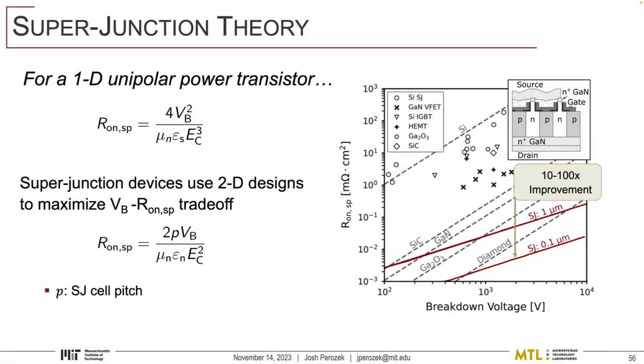But when we do that, we're able to remove this dependency on the breakdown voltage where it's a squared voltage, and we just have a linear dependence with it. That means that as we scale the voltage, the resistance grows much slower. It ends up for gallium nitride at about 1,000 to 2,000 volts. We can have a 10 to 100x improvement in theory by using these types of devices beyond the unipolar limit.